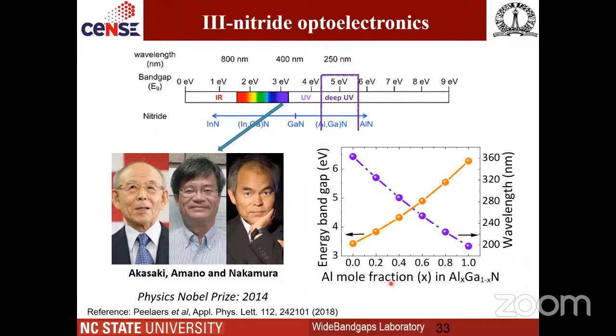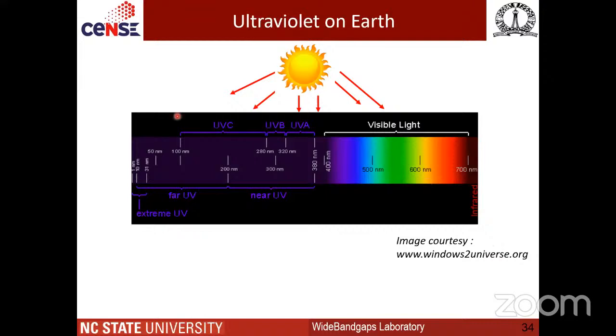So in the AlGaN material system, if you have 0% aluminum, that is gallium nitride, it enables 3.4 electron volts of band gap, which corresponds to 360 nanometers of wavelength. And when you move towards aluminum nitride, that enables a much higher band gap, which is 6.1 electron volts, and it corresponds to about 200 nanometers of wavelength. So by tuning this aluminum mole fraction, you can enable an entire range of UVA, B, and C radiations.